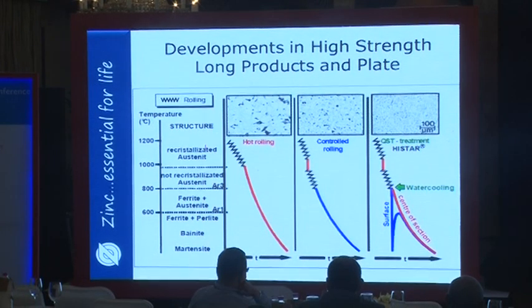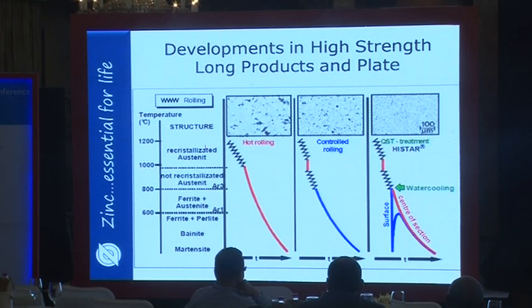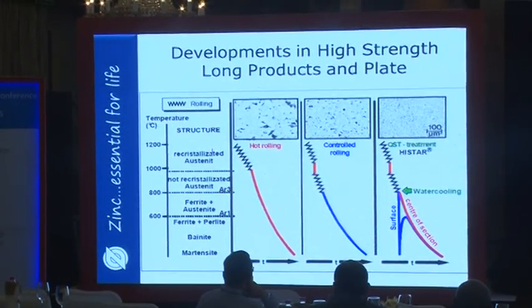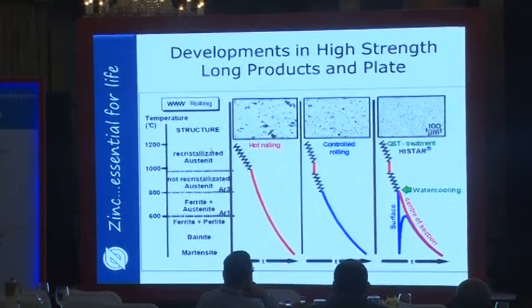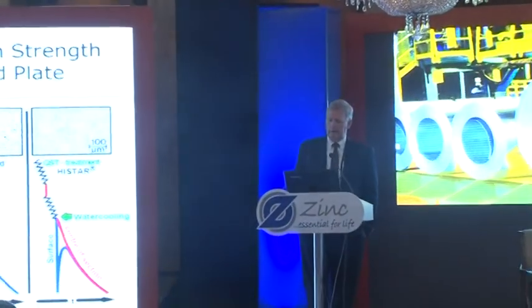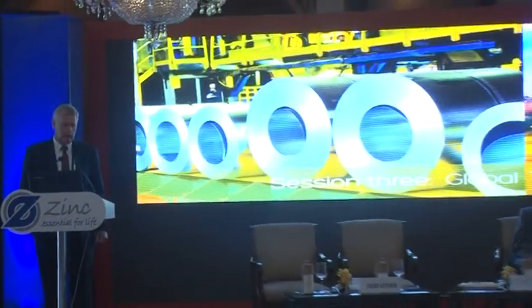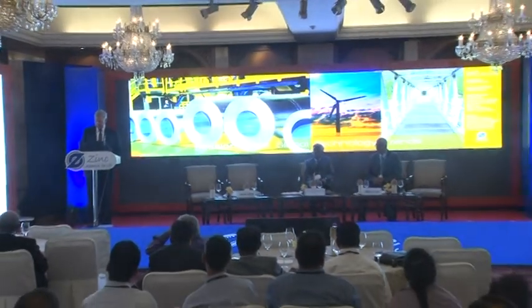So this shows an example of several processes. In the old days, the hot rolling on the left side was hot rolled and then slowly cooled. The next one is the controlled rolling, where you are doing a rolling and then cooling before and after the rolling, and coming up with a much finer microstructure, as you see here. But the most recent one is the QST process, which has been trademarked as High Star by one of the producers, where you are water cooling and then we are producing a thick plate of a much leaner composition, which means it's a cheaper steel by using a heat treatment process, which is much more similar to that used with steel sheet these days. So we're seeing the pickup or the transfer over of the manufacturing techniques from the flat product over to the plate and the shaped products here.